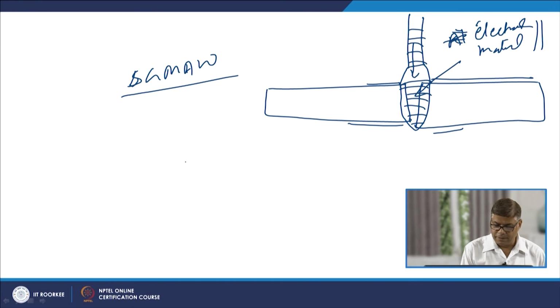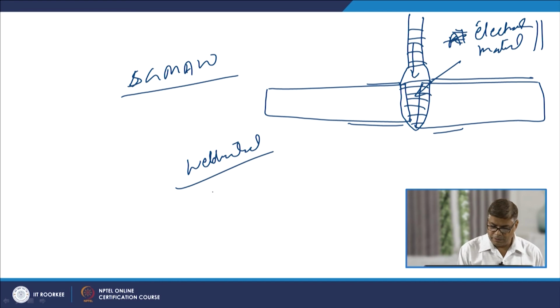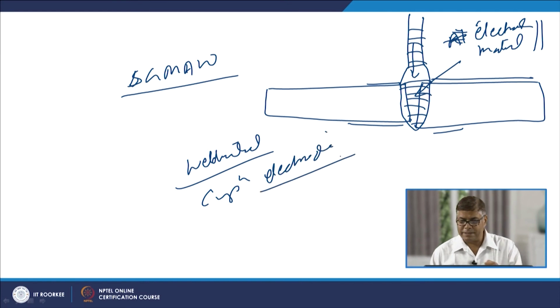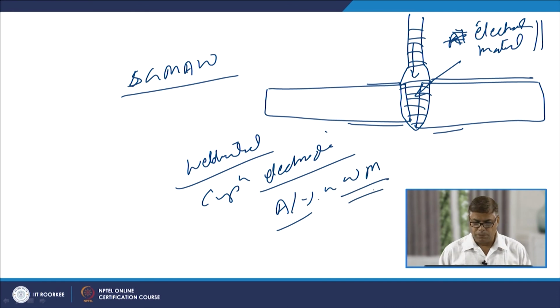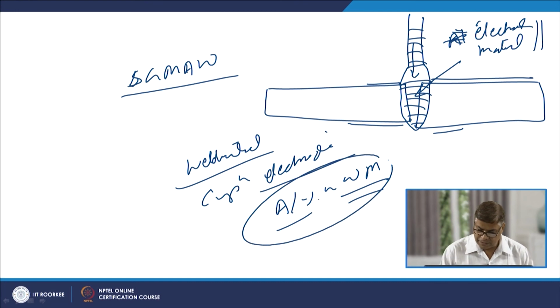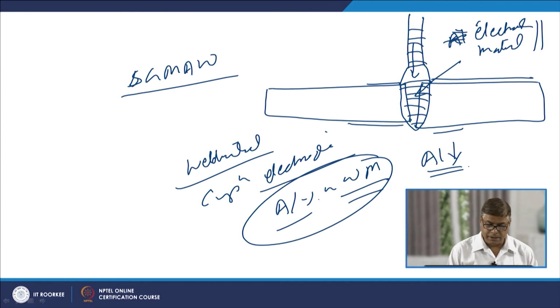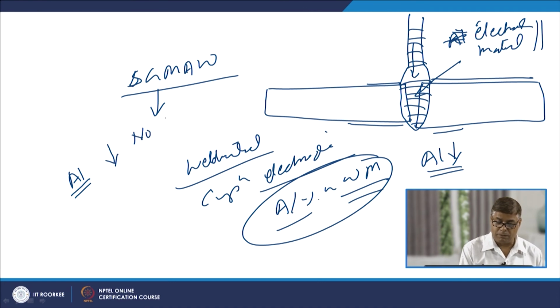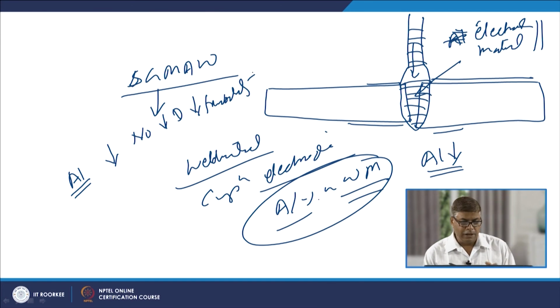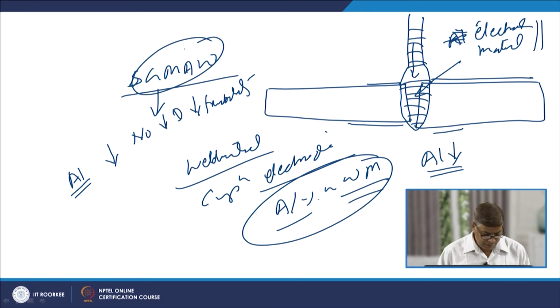As a result of this, the weld metal composition is being modified by the electrode. At the same time, whatever metal is coming from the electrode will be diluting the aluminum percentage in the weld metal. So, the dilution of the aluminum due to the addition of metal from the electrode will be reducing the concentration of aluminum in the weld metal, and therefore, in case of the GMAW process, the problems associated with the aluminum are reduced significantly. There is no problem of reduction in the ductility or formability of the aluminized steel weld joints prepared by the GMAW process.